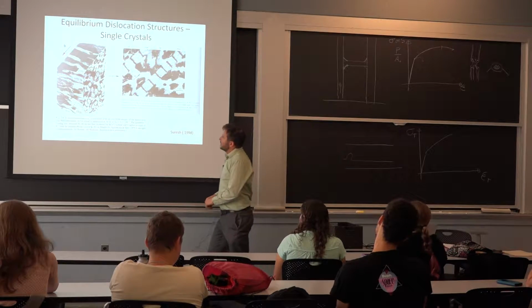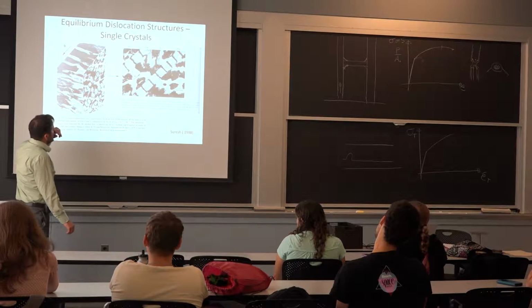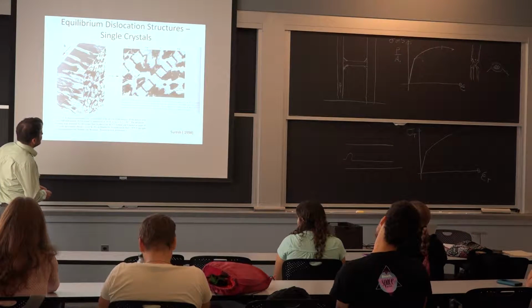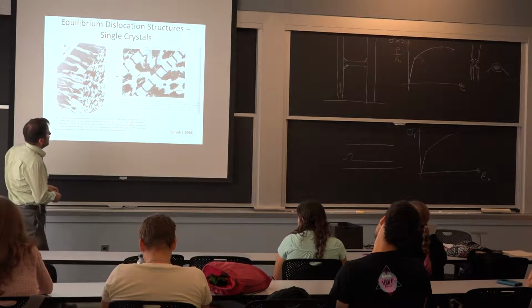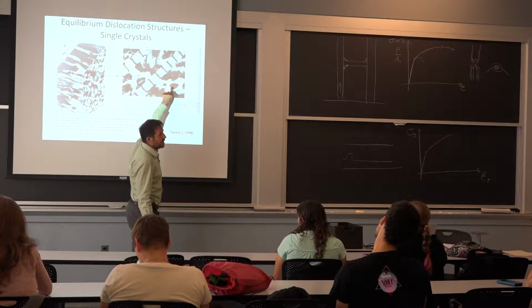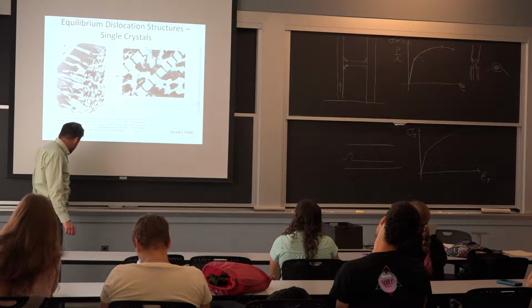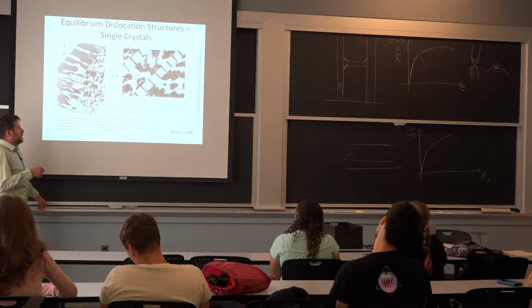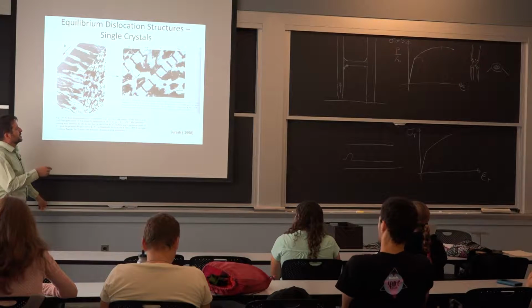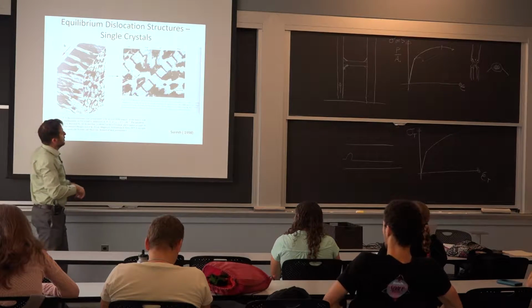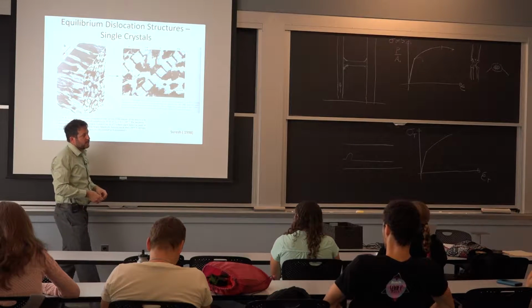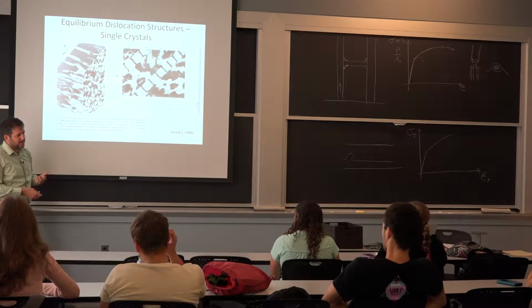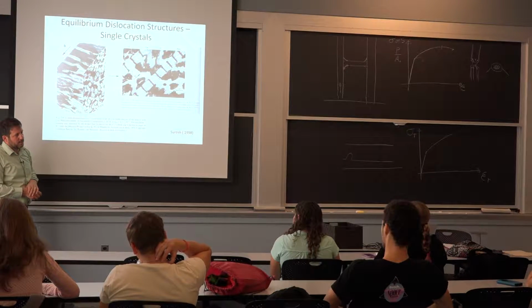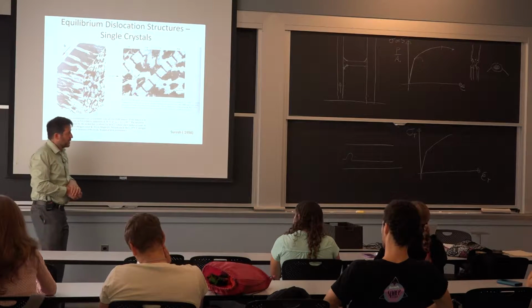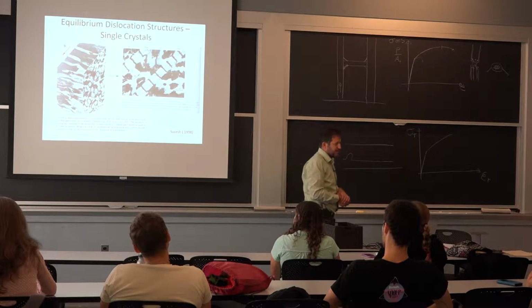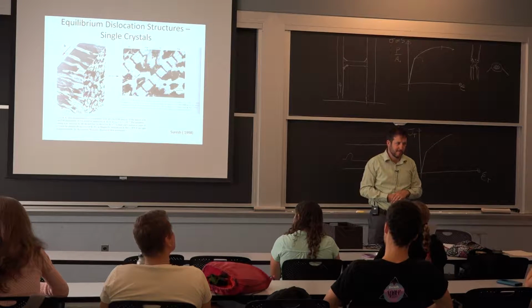So the black spots are where you have a lot of dislocations. These are TEM images, so transmission electron microscopy. This is only 1 micrometer, so you're looking at a very, very fine layer of material, and there is essentially less transmittance of the beam in an area where you have a lot of dislocations. It gets scattered a lot. So it's not an individual dislocation. It's telling you an idea of the density of dislocations in the crystal in that area. That's pretty much the closest you can get to seeing dislocations with that instrument anyway. There were other ways.